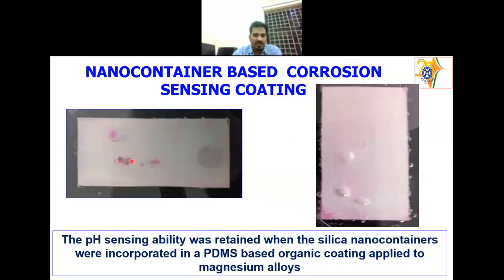Then we made a scratch here. We can find that at the scratched area, in some areas the corrosion is happening, and in other areas the pink coloration is happening. That means the cathodic reaction is happening all over here, and the corrosion is starting somewhere. So this is an example showing that the pH sensing ability of these silica-based nanocontainers can tell that corrosion is happening somewhere. You need to see that, remove the coating in that area, and do the patch-up work.